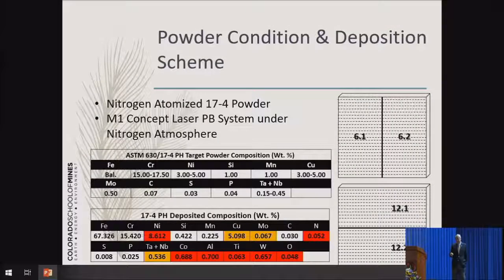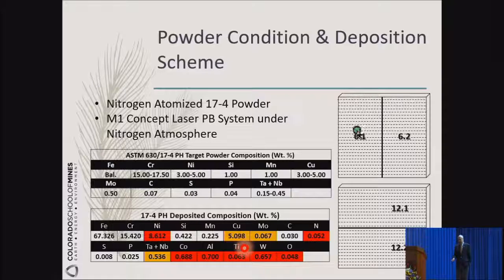Okay, so we look at the 17-4 first. If you first focus on the right-hand side here, the dashed lines mean the layers of deposit. They were all built from the bottom up. The dark line is the weld. So we welded it here going this way, and then the other one we welded horizontally, which means parallel to the build layer. One is transverse to the build layer, one is parallel to the build layer. So that's number one. You wanted to see how the deposition scheme and the welding scheme affect the property.